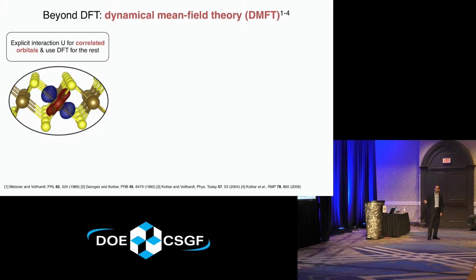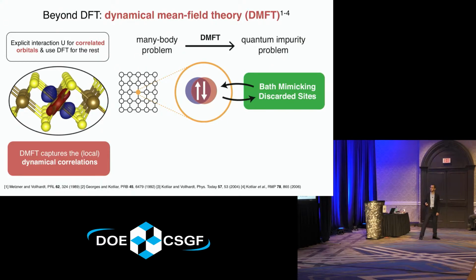In what's called the dynamical mean field theory approach, or DMFT, the idea is to perform another kind of mapping. So you have your intractable many-body problem on a lattice. You can imagine plucking out one of those lattice sites, treating the Coulomb interaction exactly on that site, and then coupling this site to an auxiliary electron bath or reservoir to and from which electrons can hop. And the key here is that this electron bath's parameters are chosen self-consistently to mimic the effect of those discarded lattice sites.